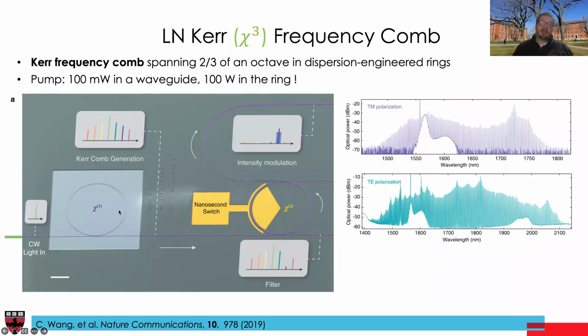Another thing that we demonstrated here, we integrated this comb source with tunable modulators, a switch channel drop filter / modulator. So this is a lithium niobate ring that basically can be tuned to pick any of these lines that are generated and drop it into this waveguide here, as shown here. And this is of interest down the road for highly multiplexed optical communications.